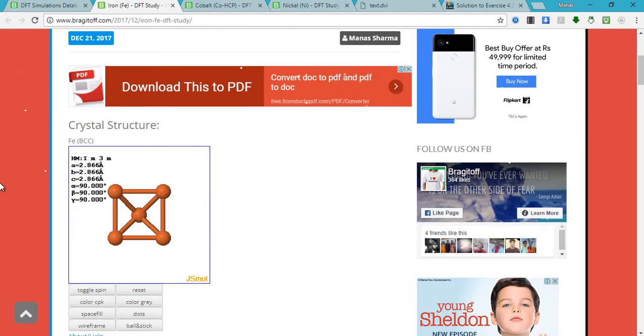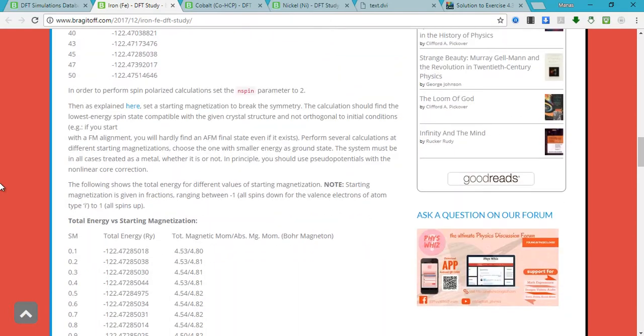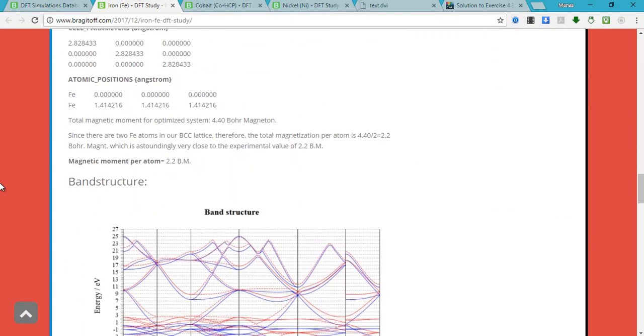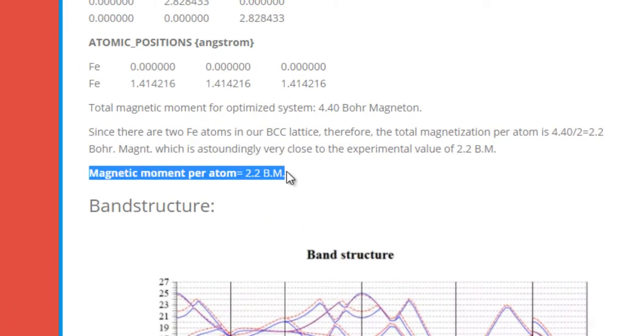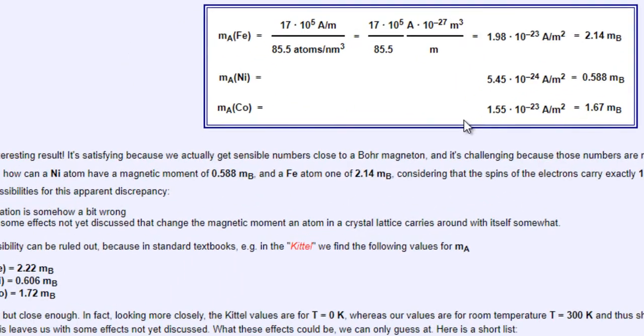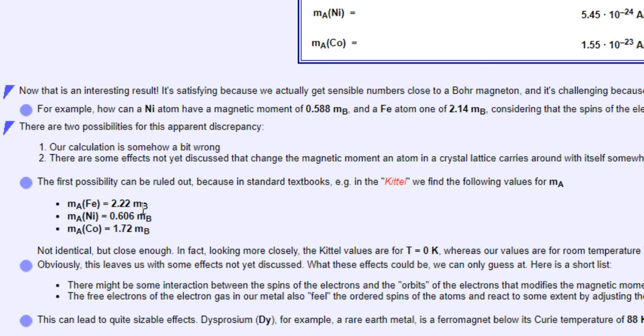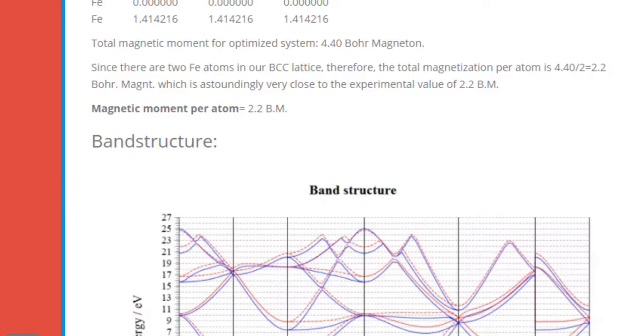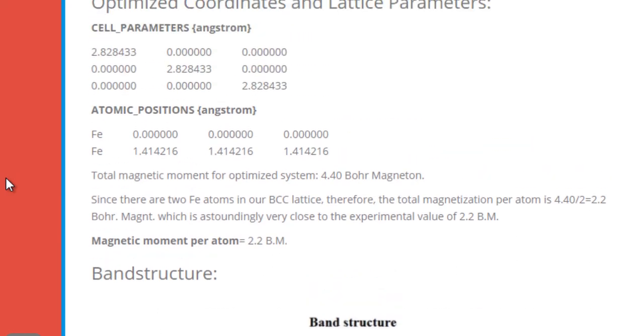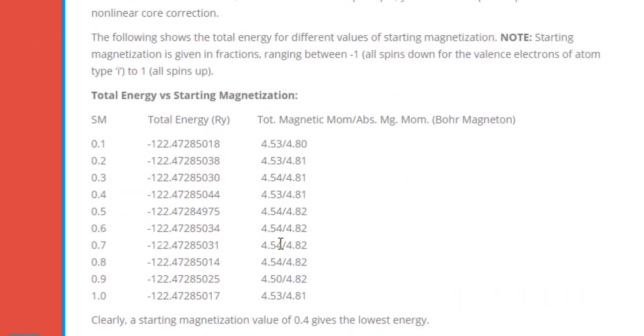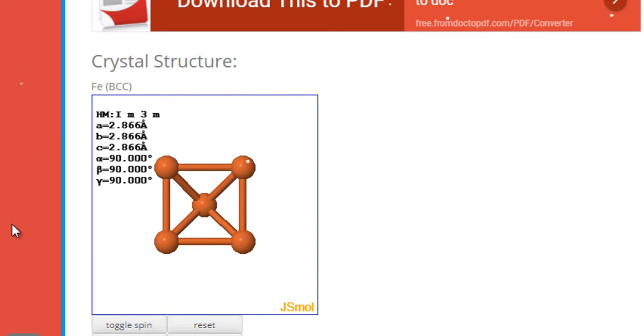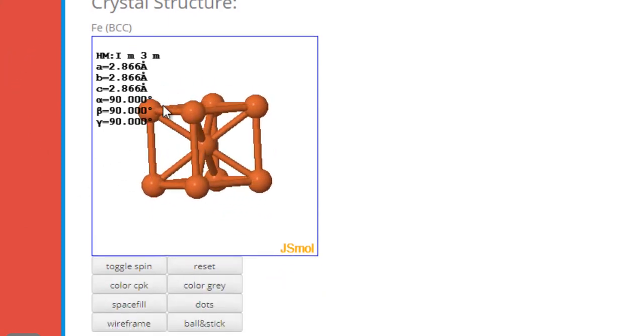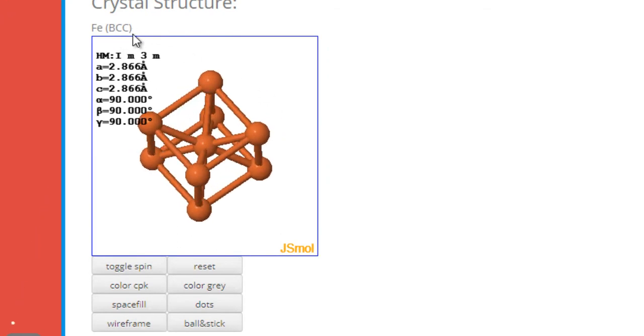When I ran these calculations I was able to successfully reproduce the experimental magnetic moment to great accuracy. My calculations result in a magnetic moment of 2.2 Bohr magneton, and experimentally — as given in the textbook Kittel — the magnetic moment value per atom for Fe is 2.2 Bohr magneton. Quantum Espresso returns the magnetic moment per unit cell, from which we can calculate the magnetic moment per atom. Fe has a BCC crystal structure.